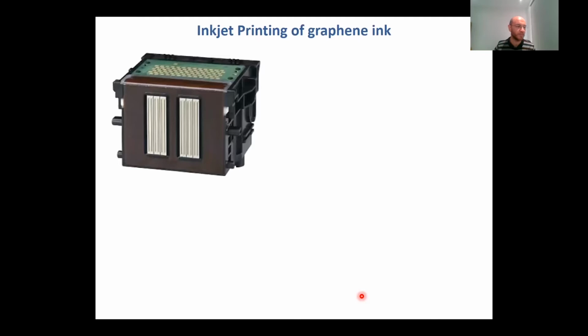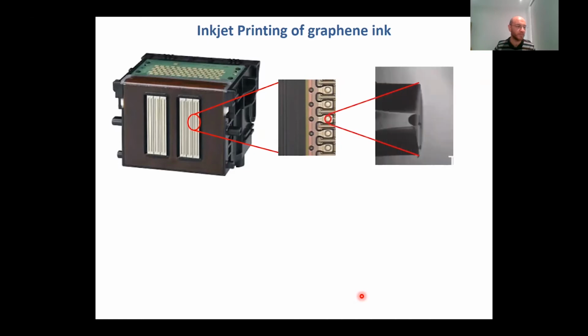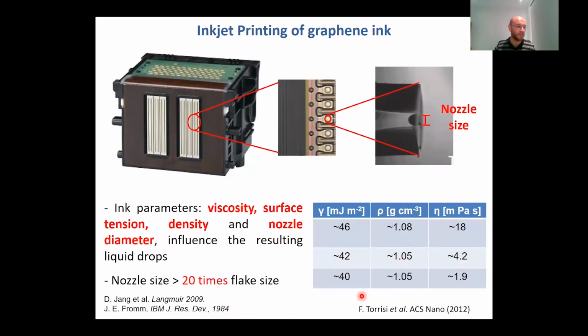So we work a lot in the area of printed electronics, focusing on inkjet printing and trying to optimize every step to control the quality of printed patterns and get reliable printing. So in inkjet printing, as you know, we normally start from a cartridge, which is made of several nozzles. The problem with the nozzle is that it has a defined diameter. So whenever we want to print through this nozzle, we need to optimize our materials dispersed in it. We normally look at flake size, or nanoparticle size if we're looking at nanomaterials, which is around 20 times smaller than the nozzle size.